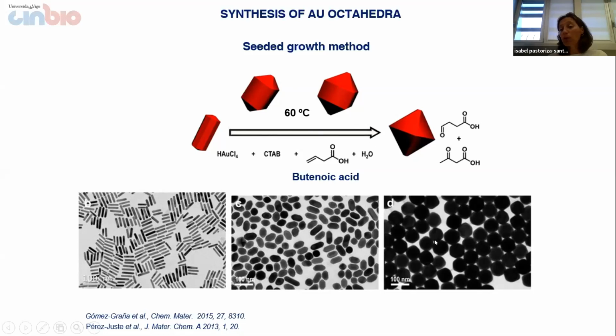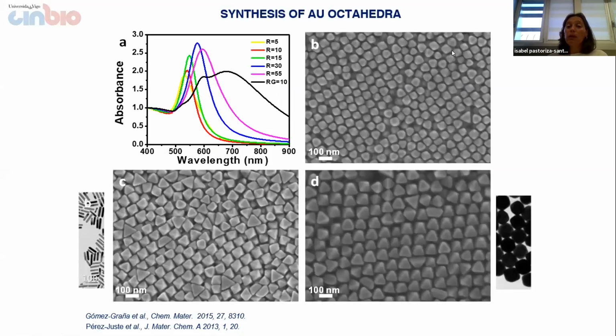This is the evolution of the particles, and the nice thing of this approach is that just by modulating the molar ratio between the gold nanorods and the gold salt precursor, we are able to modulate the size. Indeed, we are able to tune the size from 30 nanometers to more than 150 nanometers in side length of the gold octahedra. And this allows us to modulate also the optical response, as you can see here in this graph. So the particles are ready.